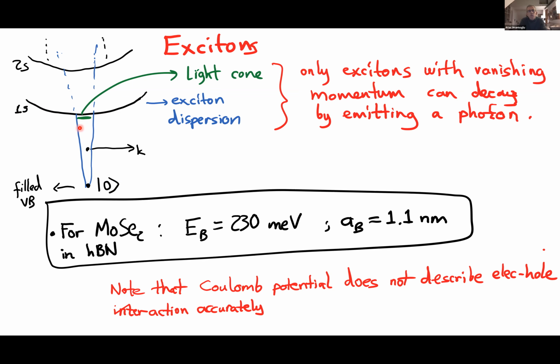And the point that I would like to make is that the mass of the exciton is even larger than the free electron mass, because it's the sum of the electron and hole masses. And it has therefore a relatively flat dispersion. But most of these excitons cannot decay, even though their energy is very comparable to the k equals 0 exciton. Only those with the smallest momentum that lie within the light cone are allowed to decay. And this will become important later on.